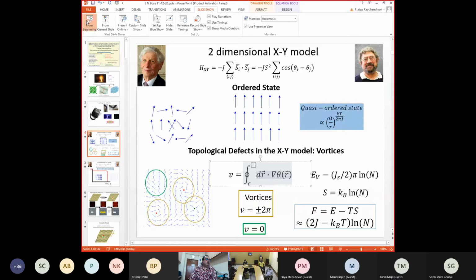All right. So let me then explain the XY model again. You have here this collection of spins which can only have component in the plane, and that means it can have a component in the XY direction. The XY refers to the plane. It does not have any component out of the plane, which is the Z direction. And you have a ferromagnetic coupling between these adjacent spins. Now, if you are at low temperature, you have actually almost an ordered state. Strictly speaking, it's a quasi-ordered state, but that is not very important for our argument here. So we will pretend that you have an ordered state at low temperature.